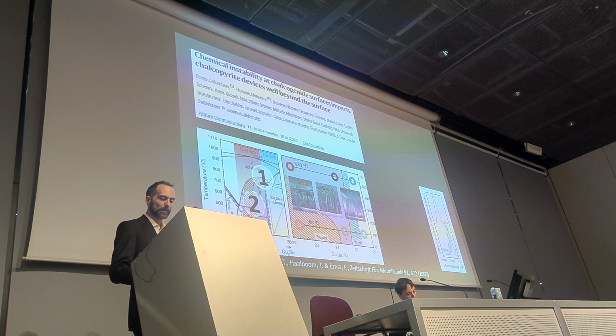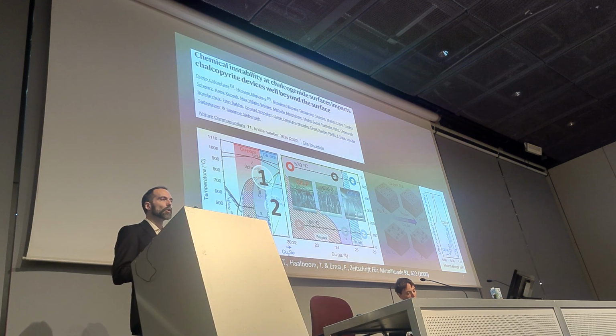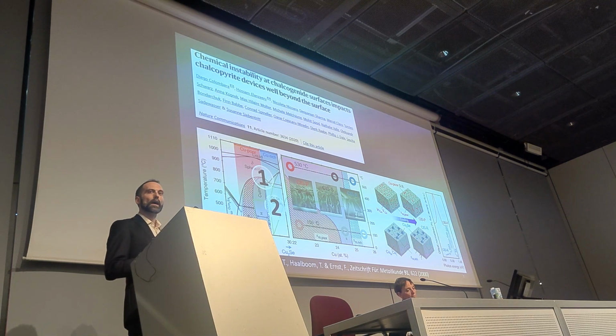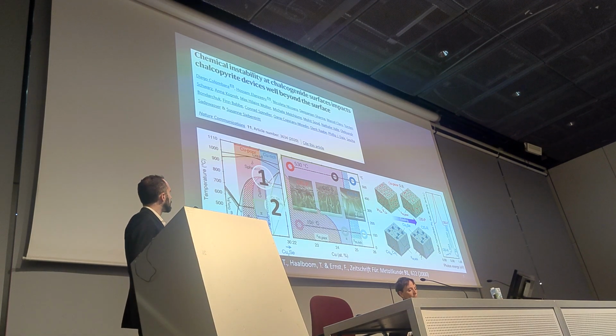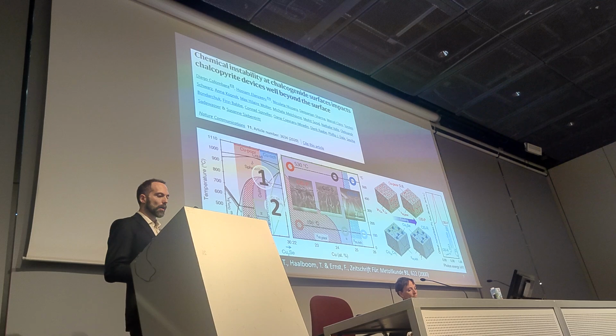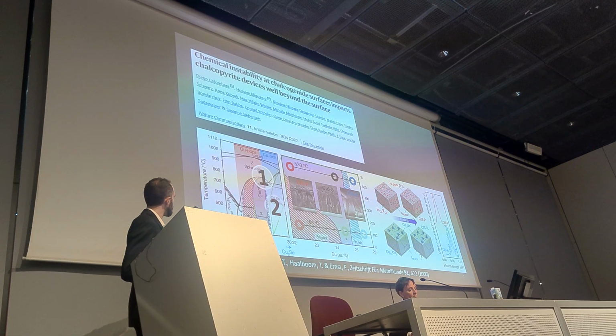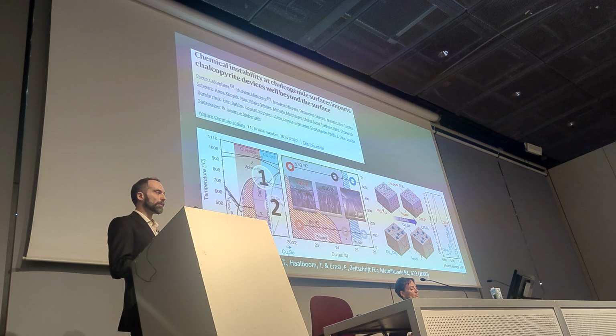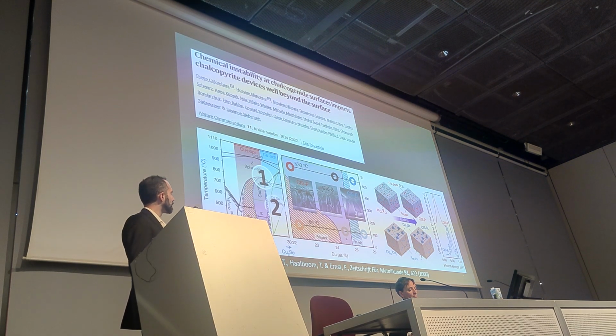So what is going on? We have to look also into secondary phases. Of course, when you grow the material copper poor or copper rich, you may end up with secondary phases at the grain boundaries. For the copper poor case, this is not a big deal because the ordered vacancy compound, the beta phase that you see here, grows topotaxially on the copper indium selenide, and it doesn't have nasty properties from an electronic point of view.